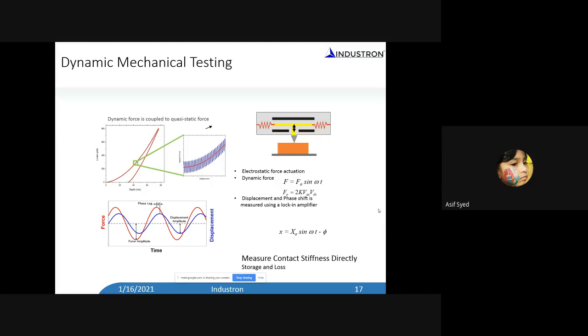Now I keep adding what all things you can do with this simple experiment of indentation. Not only measuring hardness and modulus, I have given some examples that you can do tribological characterization. With the lateral transducer, you can measure the lateral force and the friction force, you can do scratch testing and measure the adhesion strength, and you can also extend it to fracture mechanics. For example, you can measure the fracture toughness of the material.